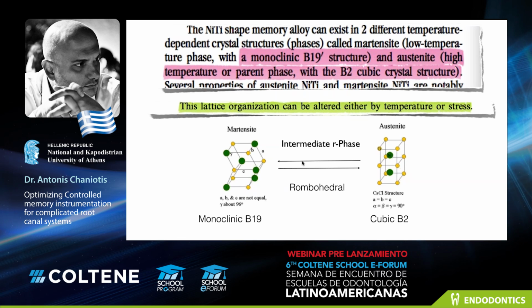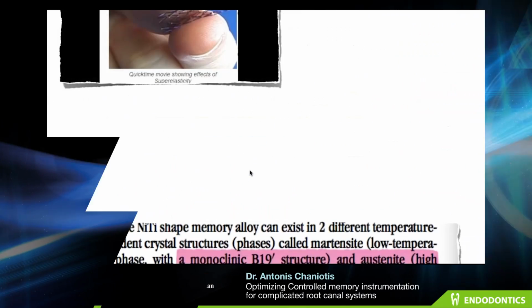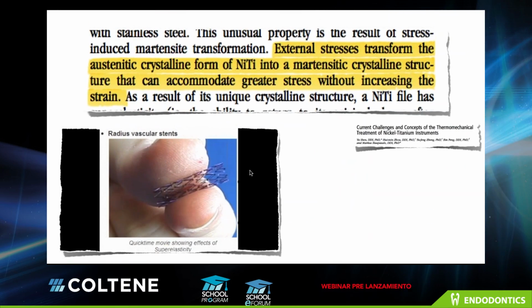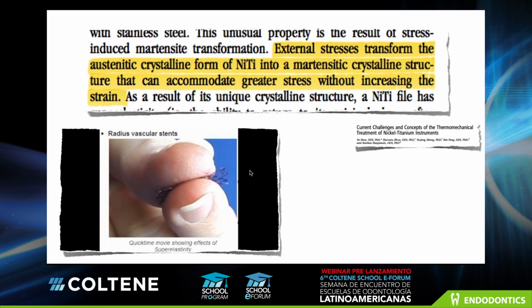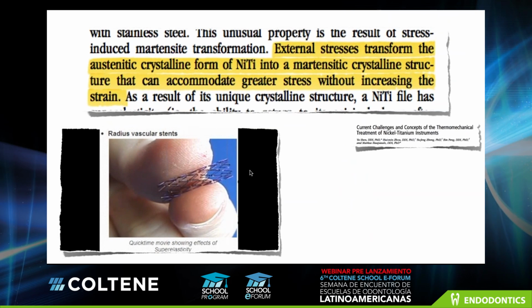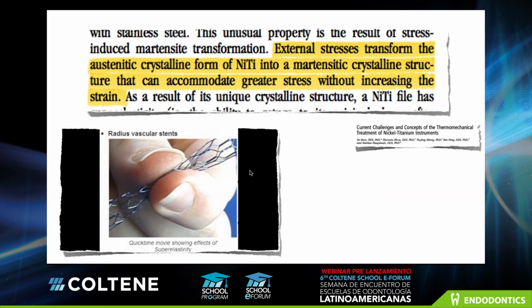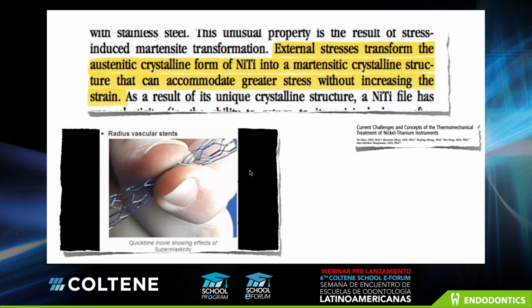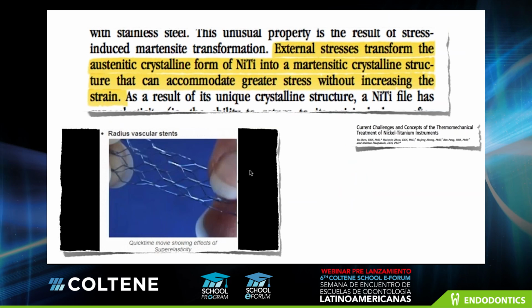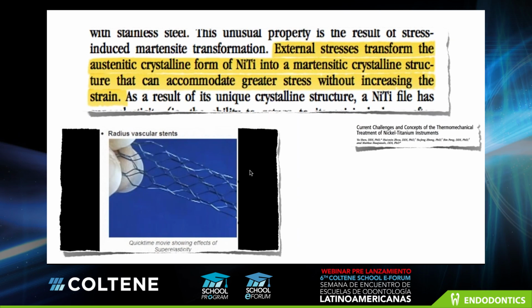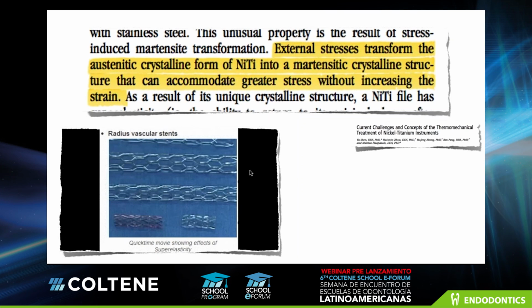When the martensite is being transformed to austenite and vice versa, the alloy goes through an intermediate phase that we call R phase, with a rhombohedral crystallographic structure. For austenitic, superelastic, shape memory nickel titanium alloys, like the radius vascular stent that you can see here in this video, in body and room temperature, it's austenitic. The external stresses that you apply with your fingers will transform the austenitic crystalline structure into a martensitic one that can accommodate greater stress without increasing the strain.